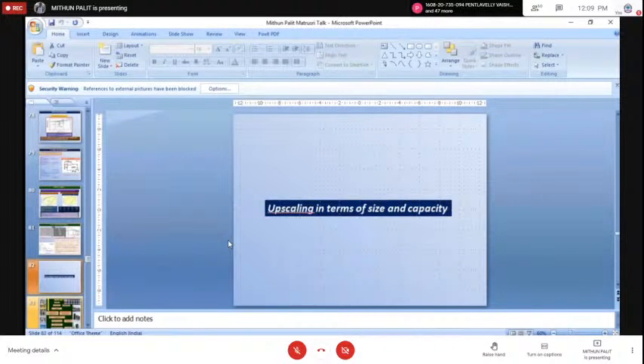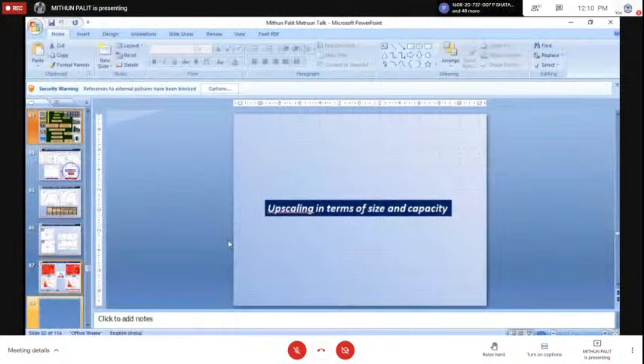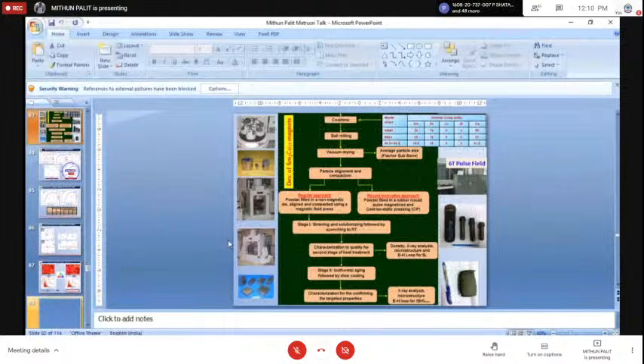So these magnets, what we are showing here, the PM route and all, the scale of operation is very small, up to say half a kg or a maximum of 1 kg. Therefore, in DMRL, since we are working for larger systems, we need to develop a larger magnet. So accordingly, we have innovated a different process route. Here we have used a technique called cold isostatic pressing.